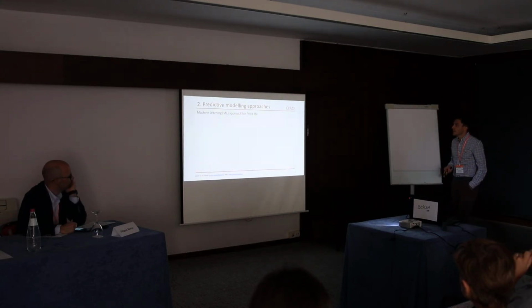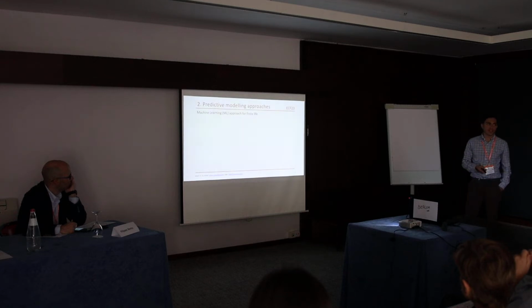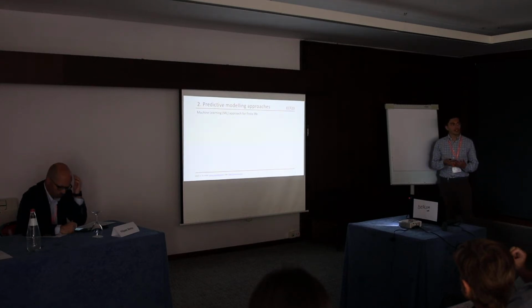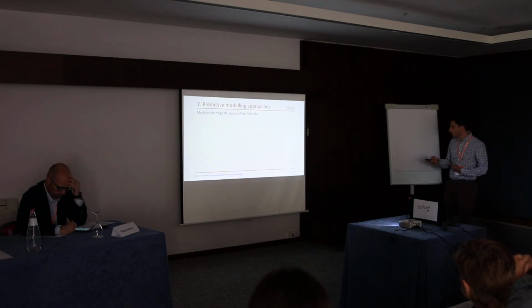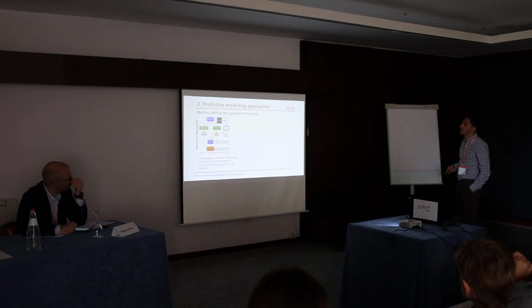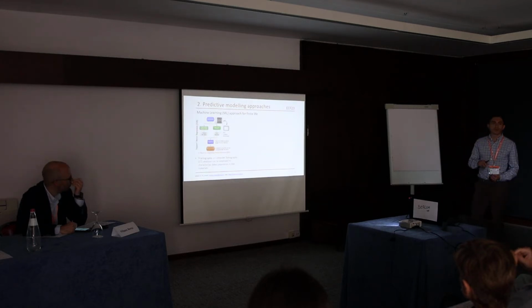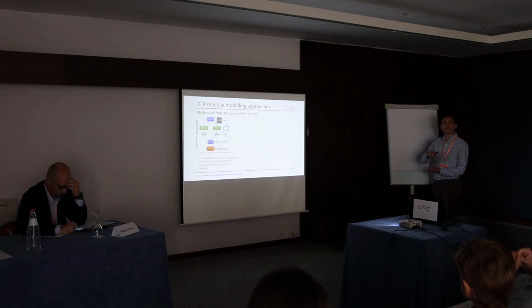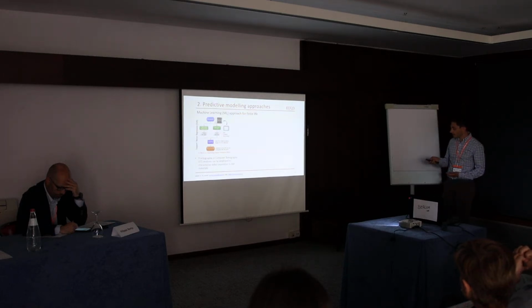On the other hand, machine learning has been employed only very lately, I'm talking about 1 or 2 years. One of the few works on this employs support vector regression. There are samples which have been analyzed through computed tomography, so we have all the statistical information of all the porosities, and then they were tested under fatigue conditions, and they try to make predictions.